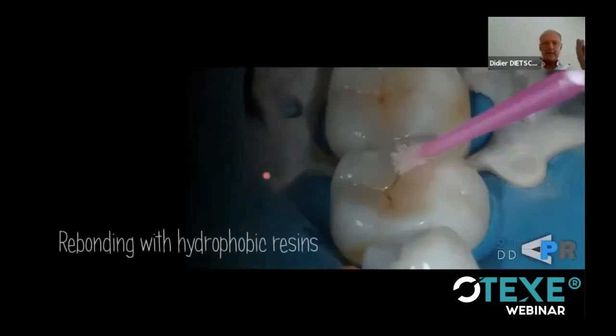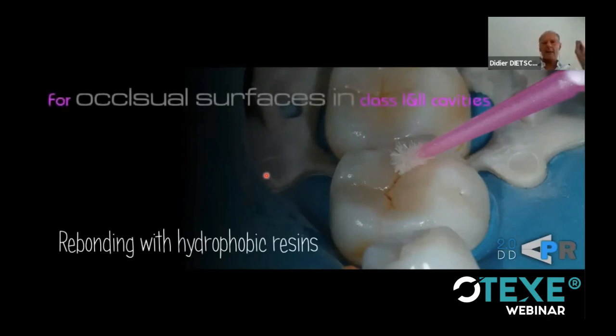There is a last key element in regards to class 1 and 2 restorations, which is the rebonding with a hydrophobic resin. That's something that I didn't do for maybe the first 5 years. And in the early 90s, I started to use that technique, and I've seen a huge difference. There is no research really supporting this. It's really by clinical application. By doing thousands of those restorations, I can really confirm that it's making a big difference.